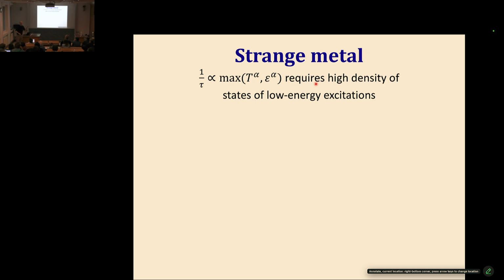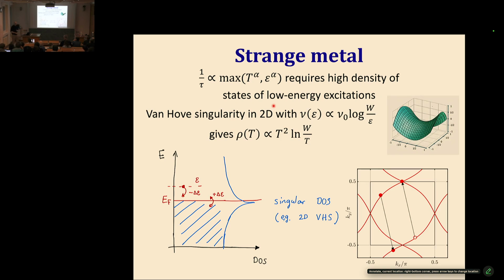So we saw that in a Fermi liquid, the excitations that scatter are the same electrons, and they have a constant density of states at low energy. It's really scattering of an electron off a quasi-particle, quasi-hole pair. To get something different, we'll have to have a much higher density of states at low energy. And we already saw an example of where this high density of states at low energy might come from. Suppose we somehow tune our system such that the Fermi surface is exactly at this point of topological transition between one connectivity of the Fermi surface and another one.